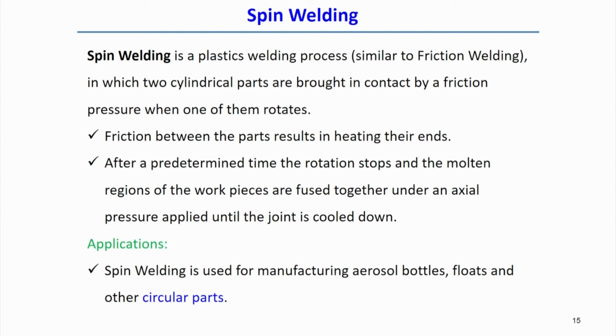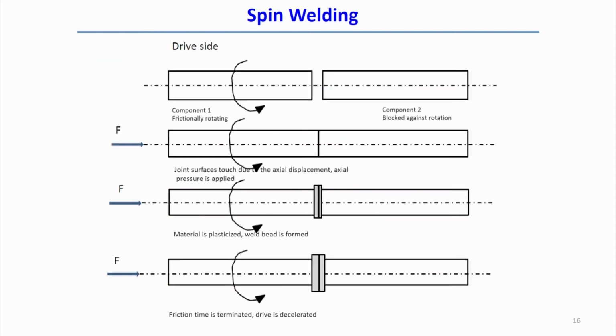A typical application is the manufacturing of aerosol bottles, floats, and other circular components by using the spin welding process. We can see how the spin welding process works. One drive starts rotating one component, the frictional rotating component, and the other component is blocked against rotation, that means we keep it stationary. Then after rotation starts, we keep the interface between the two components in contact, and finally the material is plasticized and a weld bead is formed with the application of the axial pressure, and in the fourth stage rotation is blocked. That means we can block the rotational speed and keep on holding the axial force until it is cooled down to room temperature.